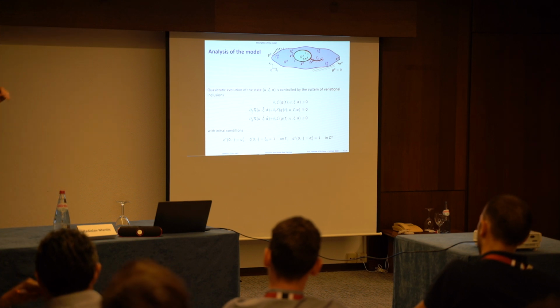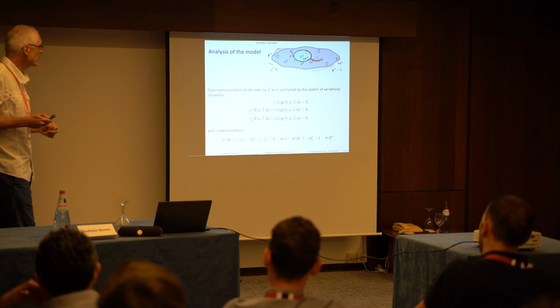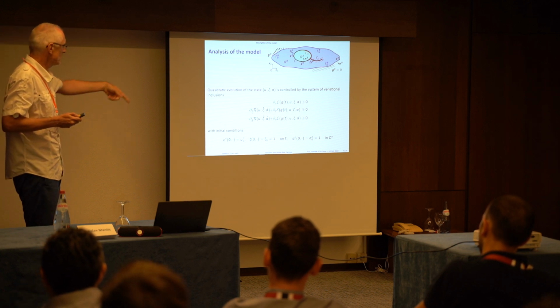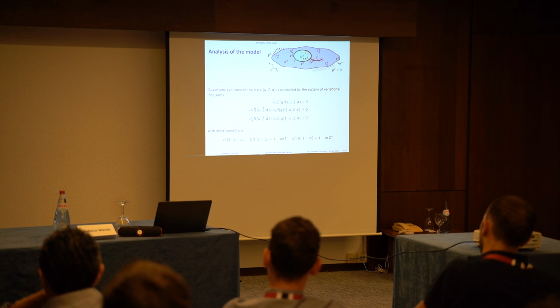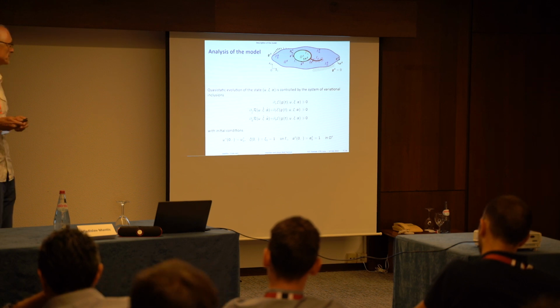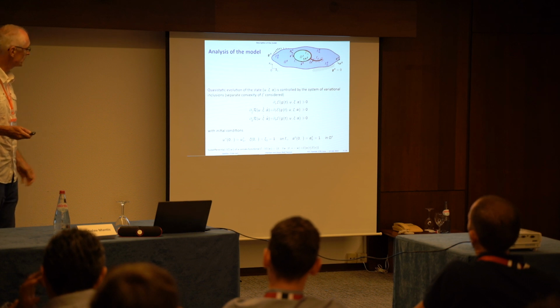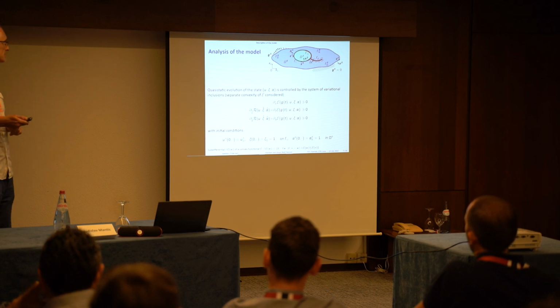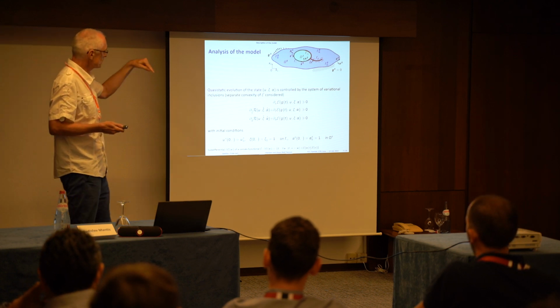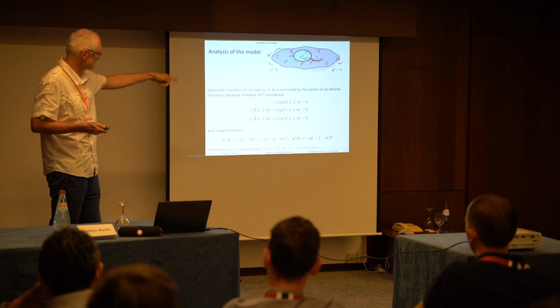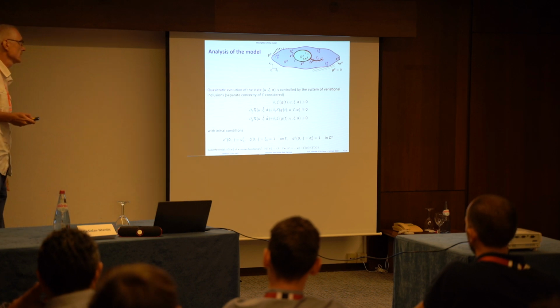In fact, the first one is a condition of equilibrium, and the last two are flow rules for damage, either on the interface zeta or the phase two parameter alpha. The computations rely on the convexity of epsilon with respect to each separate variable. That's the reason why I can write these relations in terms of subdifferentials.